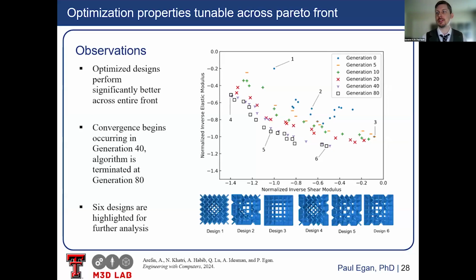And we also put in a few heuristics to help it converge faster, which was seeding it with homogeneous designs. But what you'll find is through the optimization, you might expect the homogeneous designs to do the best in the extremes because they're only BCC or only cubic unit cells, but actually some emergent properties from combining the two unit cells, so 4, 5, and 6, actually outperform the homogeneous design. So having them as seeding designs helps you get to a good space in the design space and then use that genetic algorithm to further improve it. And so you can see here at generation 80, we mostly converged. And you can see you can select designs that are going to be good in shear modulus or good in elastic modulus or some combination of them, depending on your system you're trying to optimize for.